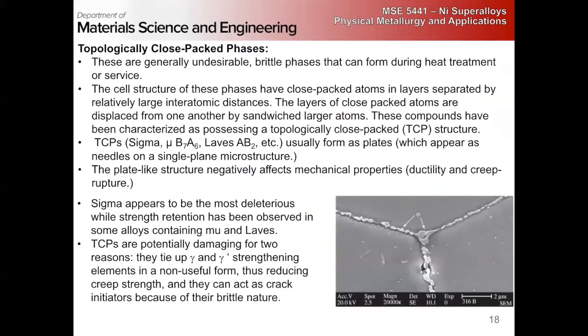And of course, we also have other phases that can form. There's a large group of generally undesirable phases called topologically close-packed phases, and these are brittle intermetallic-like phases, right? So the name is a little confusing. In the unit cells of these, we have layers of close-packed atoms separated by larger atoms sandwiched in between, right? So the name that these have been given is topologically close-packed: close-packed layers with other atoms in there, so the close-packed planes are not separated by their usual distance, right?